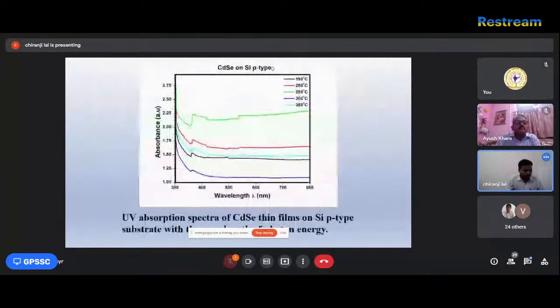Absorption and transmission studies are carried out in the wavelength range 300 to 800 nanometers to investigate the optical properties of CdSe thin film. So the variation of absorption A and transmission T with the wavelength: a lower grain size results in an increase in the scattering of photons at grain boundaries, contributing to the decrease in transmittance.